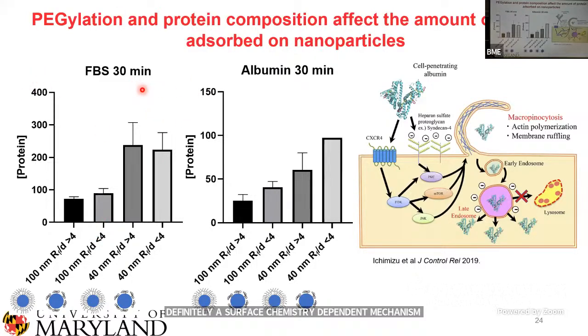We did an incubation with just FBS, which is a conglomerate of a whole bunch of different proteins, and then also just albumin by itself. We're starting to see some interesting effects: when you have an albumin coating, there's maybe a bit of a trend that more albumin adsorbs onto the surface when you have an RF over D of less than 4. So these are your less densely pegylated particles. When you use the mixture, in terms of the total protein content, there doesn't seem to be much of a difference. So we're starting to think that albumin is a really key player here. Maybe this is part of the difference between all of these. But the key thing is we still have a lot of work to do to figure out what the proteins on these surfaces actually are.